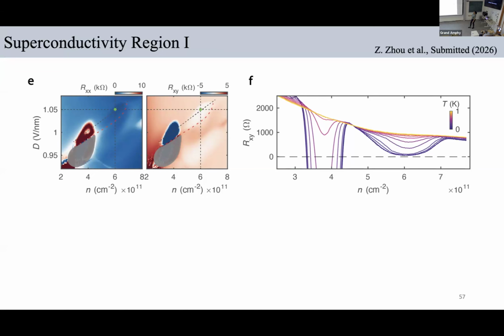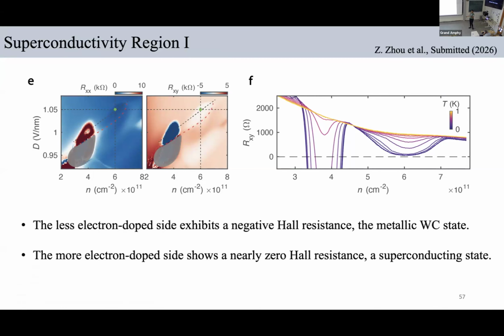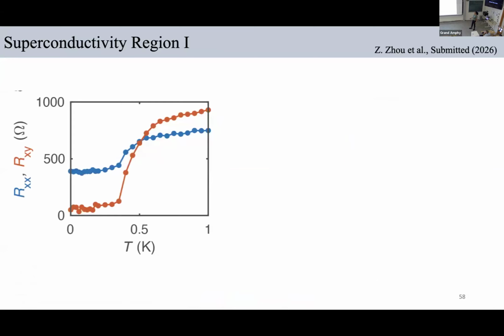And then, just to show you why we think about this connection: this is a metallic Wigner crystal. Here there are some unpinned carriers, which are all electron-like in nature. And we see a kind of direct connection, if you can imagine this blob is here, etc. They also melt at the same time, the superconductor and the Wigner crystal. We tried fitting here, we could not do it meaningfully, and hence we gave up and just submitted whatever we had.